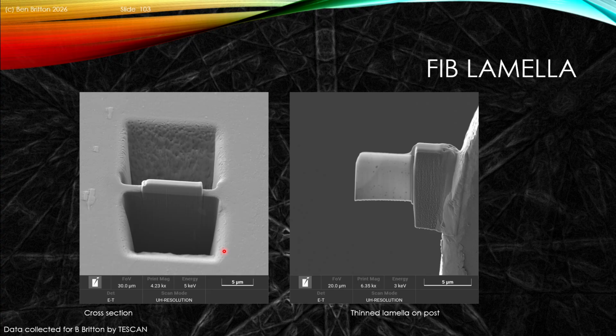So this is an example of a prepared lamella that was kindly prepared by colleagues in Tescan. And so this lamella effectively is now cut out. It was cut out from either side, so we've got trenches either side. We've got a platinum coating on the top layer. And then the sample was effectively extracted and then welded on the side of a copper grid. The grid is over here. The lamella is sitting here, and then it was thinned.